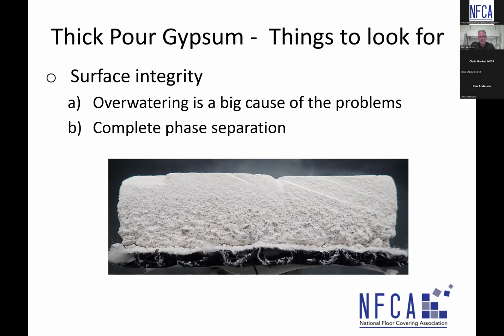That's a great slide. Yep. Really sums it up. It does. And we see that all too often, unfortunately. It's not the gypsum's fault. That's why I say gypsum gets a bad rap. It's an engineered material, and when mixed with the right amount of sand, the right amount of water, you have a good material. But what we see here in this picture is we see it all too often on job sites, unfortunately.